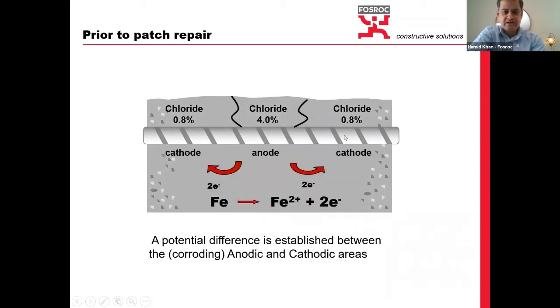Both the areas have chloride content more than the threshold value, which is 0.4% by weight of cement. This is 4%, this is 0.8%. Both of them are higher. However, the areas where you have cracks have a higher chloride level. That means it has a higher potential as compared to the adjacent areas. So it will act as an anode, and the adjacent areas are still safe. In a cement matrix, they are cathode.